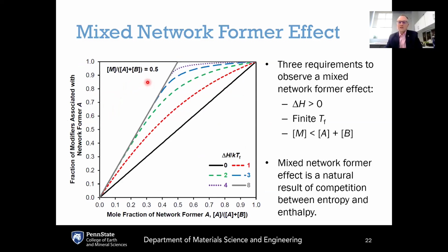These statistical mechanics provide a natural description of the mixed network former effect in glasses. The mixed network former effect is a nonlinear variation of glass properties where you have a fixed amount of network modifier here, a fixed amount of M, and you're just varying the ratio of how much of one of the network formers you have relative to the other one. So this x-axis is now the mole fraction of network former A, so it's the concentration of network former A over the total amount of network formers here, A plus B.